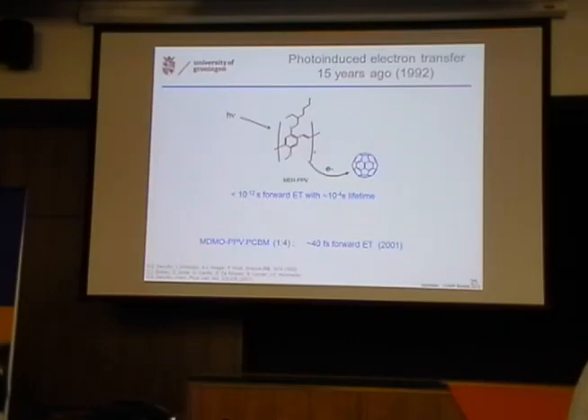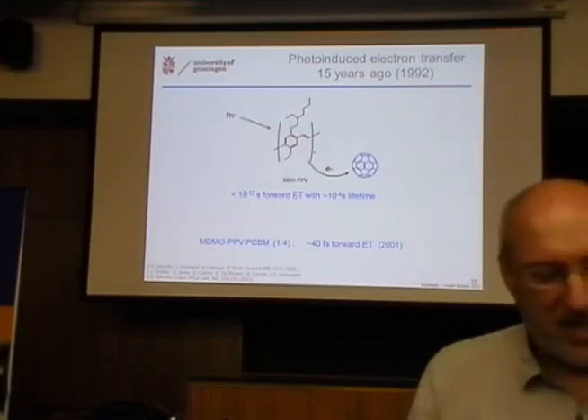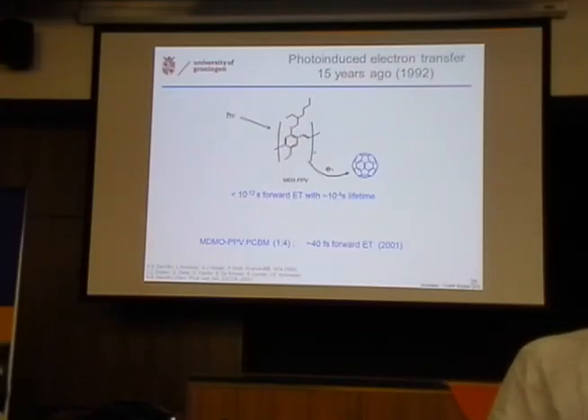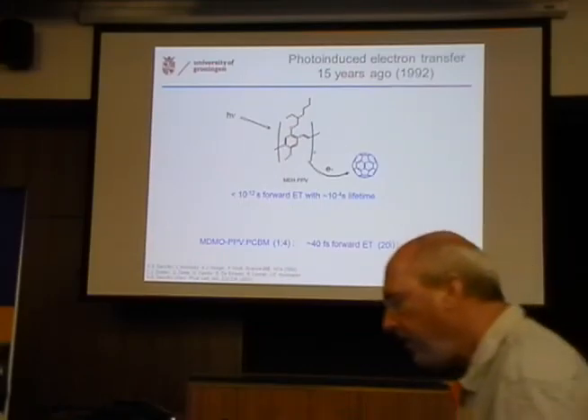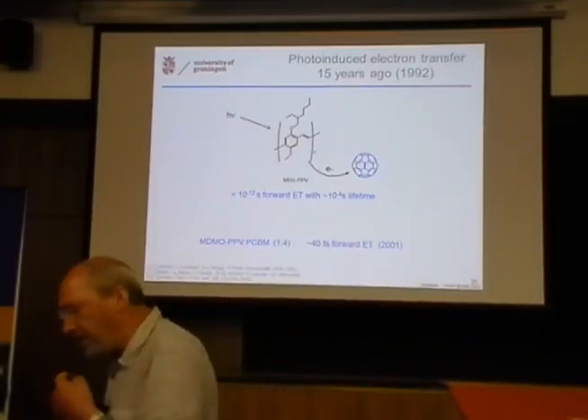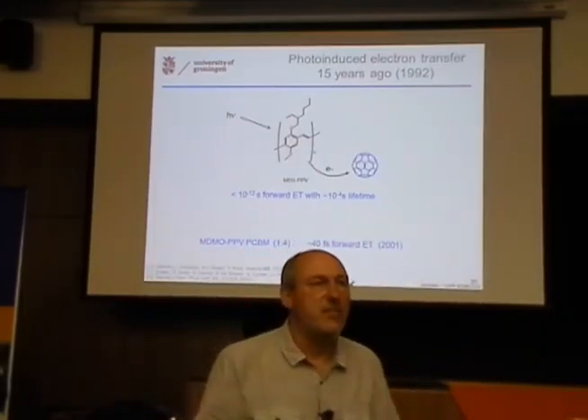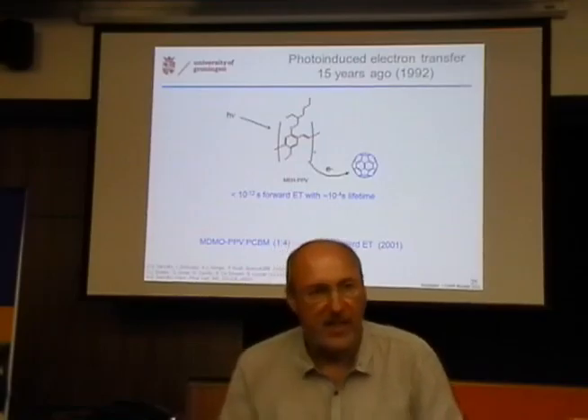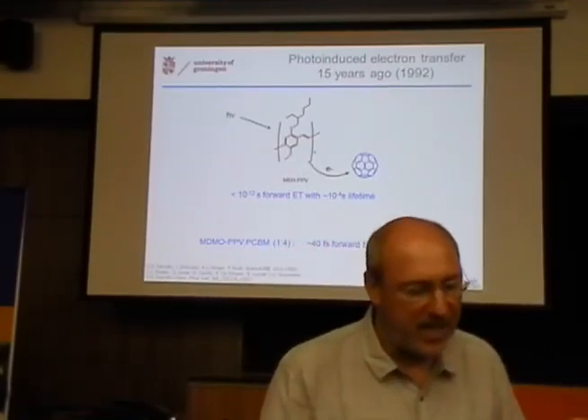One group said this is just quenching by energy transfer, and the other group said this is quenching by electron transfer. The Santa Barbara group was the one that said we have charges, we have electron transfer, and that was the right interpretation. And so this was the discovery of photoinduced electron transfer from a conjugated polymer to an acceptor, which in this case is C60.